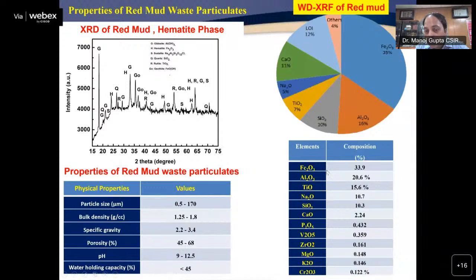We come to the conclusion that iron oxide is 33.9%, then alumina oxide, titanium oxide, sodium oxide, and the particle size of this red mud was in the range of 0.5 to 170 micrometer, with a density of 1.2 to 1.8 gram per cc. And you can see the water holding capacity is also more than 30 or 40%. It means once it is disposed in the open land, it can transfer the ions from soil to the water and also the agricultural land, which creates another problem.